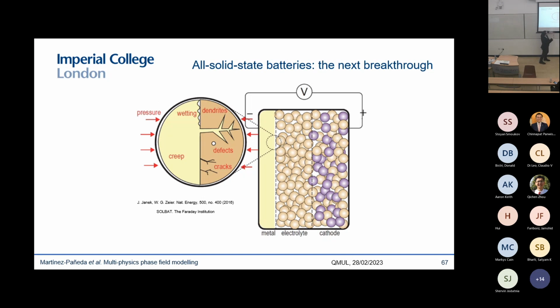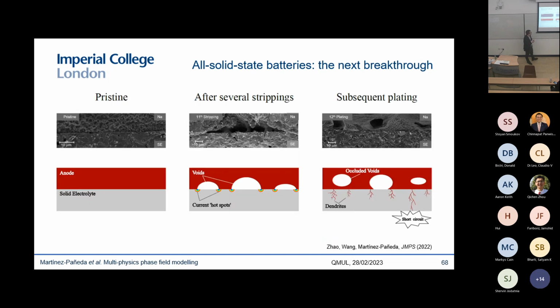And particularly problematic are these dendrites, which are needle-like filaments that initiate at the lithium anode and then propagate all the way to the cathode and therefore short-circuit the battery. And you can see it very nicely here. These are some very nice experiments from Peter Bruce's group in Oxford.